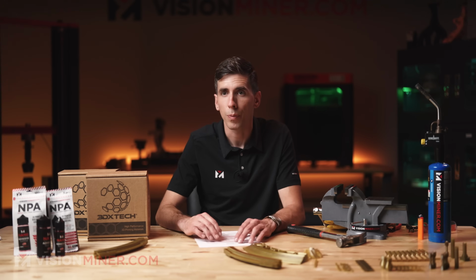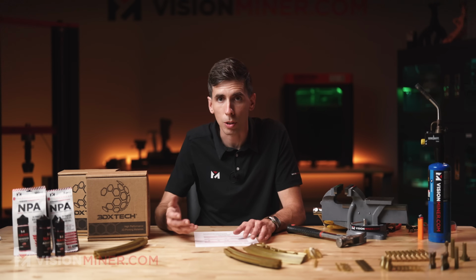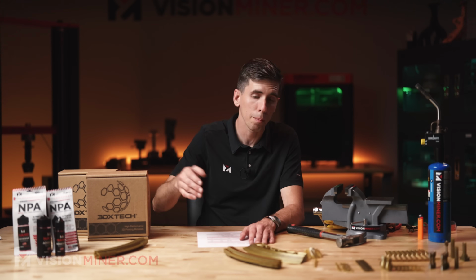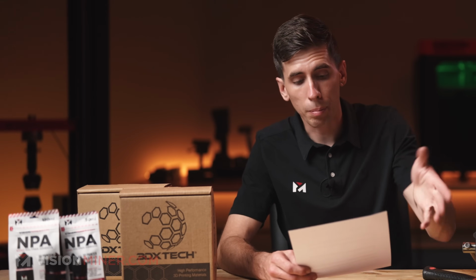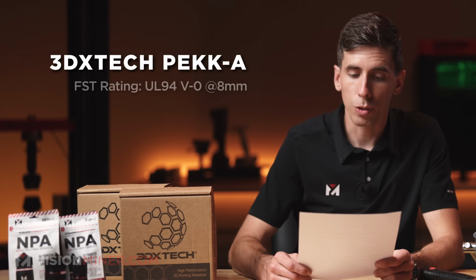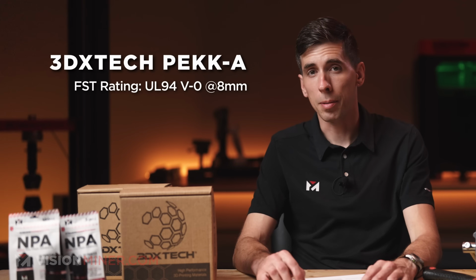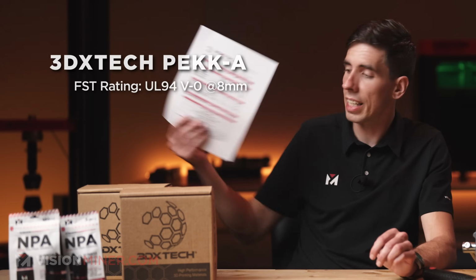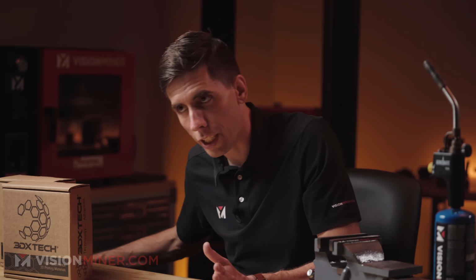And the heat deflection temperature is about 150 Celsius. And that's the max real continuous long-term use temperature. You can go a little bit higher for short periods of time, but if you're in a 145 Celsius environment, then this stuff will do pretty well for you. And it's got the flammability rating for the base resin of UL94 V0 at 8 millimeters. So that's the TDS, and let's check out some parts.